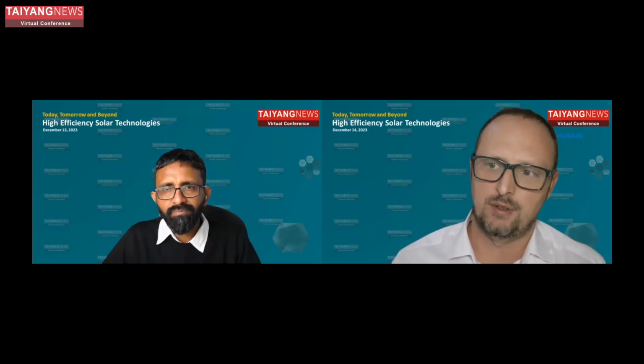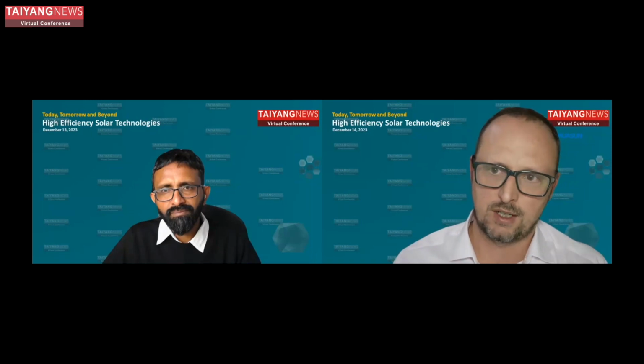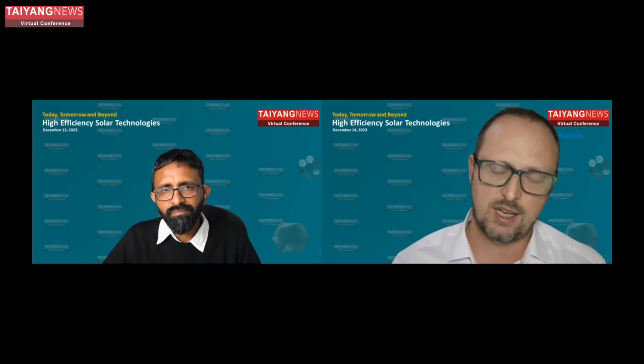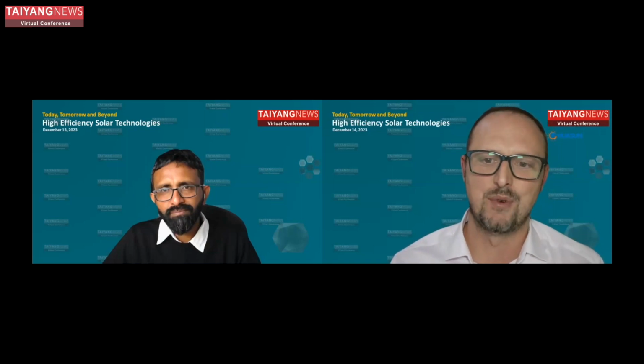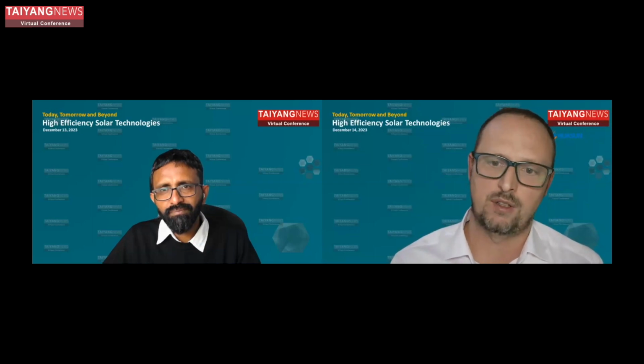But that happened already. So if you see modules and systems from them that were prior to 2007, they are okay. But if you see them after 2007, it's incredibly stable performance and customers know it. And that is kind of the strength of heterojunction. But Sanyo, basically Panasonic, didn't invest anything in R&D, in real production R&D, since 2009, 2010. So that time we can now very quickly improve in efficiency and in cost. And this is the super big chance of heterojunction.